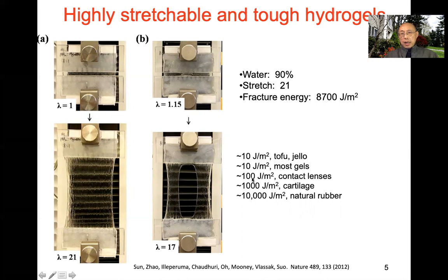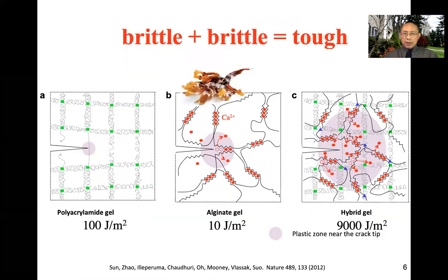Contact lenses, 100 joule per meter squared. Cartilage, 1,000. Natural rubber without any reinforcement, 10,000. So our hydrogel with 90 weight percent water has a toughness comparable to natural rubber. Very tough behavior. Now, this behavior comes from something like plasticity. So we made our material by mixing polyacrylamide gel and alginate gel.